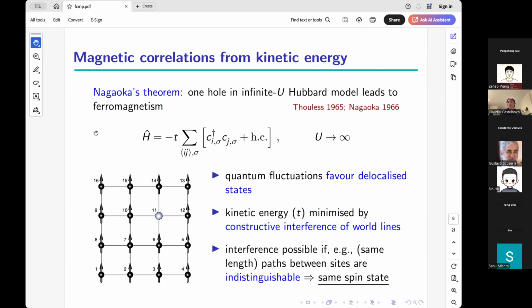In an infinite U model, if you are exactly at half filling, 1 electron per site, you have a complete insulator. This Hamiltonian annihilates that state because nothing can hop, nothing moves, and you have each electron with its own spin and nothing else. And then Nagaoka pointed out that if you remove 1 electron and you create a hole, like in site 11 in this picture here, then the hole is able to move around.